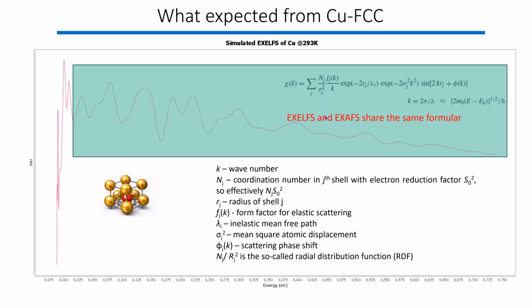So there is no critical difference between EXAFS and this technique. In terms of the source and how we collect information, they are a bit different, but in terms of the formula itself, they share exactly the same formula from this dipole effect, basically. The slight difference, if you look at the formula, is that the neighborhood atoms term is coupled with the so-called amplitude reduction factor, which may vary between X-ray and electrons, because fast electron interaction with the K shell electrons and X-ray interaction with the electrons are slightly different. Otherwise, the rest are the same, basically.